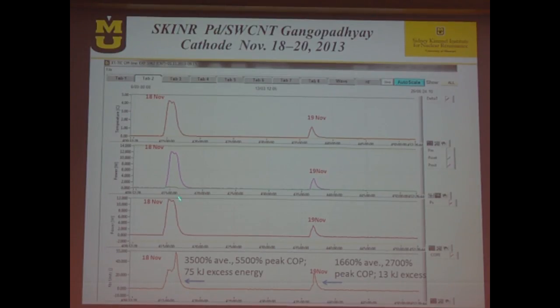And then it stopped by itself, and after 20 hours, it started again. But this time, this was overnight. This time we were in the lab. So immediately what we wanted to see is if we are measuring rightly the voltage, because for the current, you have to open the circuit. We didn't want to open the circuit. The moment we touched the poles, the voltage dropped. And as you can see,